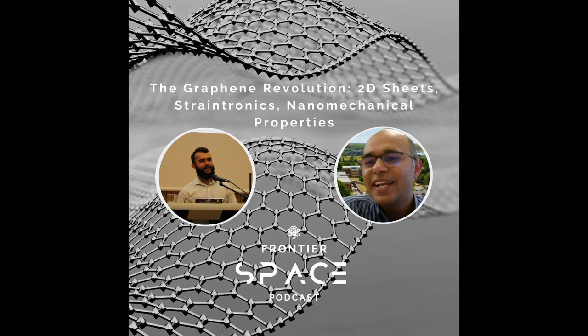However, when you reach the maximum limit of 16 nanometers of wrinkle height, it starts bending. Whatever I'm talking about is just an atomic layer of graphene. If you have a thicker layer of graphene, you can go even beyond that height. But I'm talking about the atomic layer. So if you have an atomic layer, you can achieve a maximum of around 16 nanometers, then it starts bending, because the bending stiffness is not enormous in a single layer of graphene.